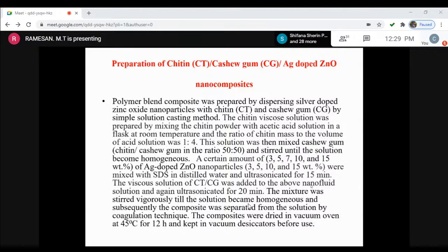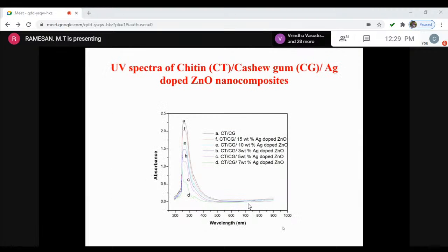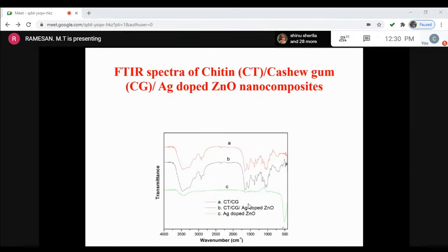Here also we prepared in a similar way, the only variation being 3 to 15% silver doped zinc oxide in that system. The mixture was vigorously stirred and finally dried at 45 degrees Celsius for 12 hours. This is the UV spectra that we have taken. You can see that the absorbance of the peak decreases with the loading of nanoparticles, and 7 weight percentage shows the lowest intensity, meaning the peak height is minimum for this 7 or 8%, which means this 7 or 8% has good properties. This is the FTIR spectra.